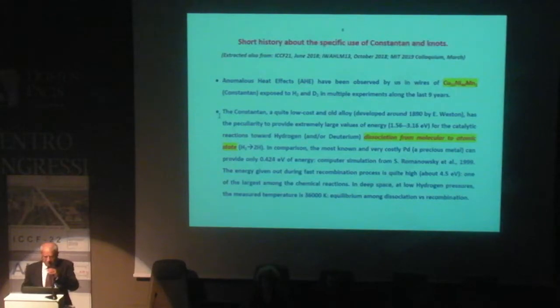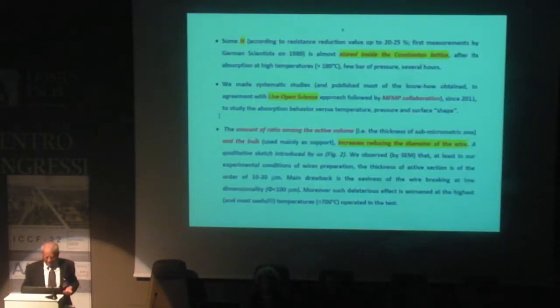Before, we concentrated on using knots, because the knots don't need energy to have non-equilibrium, but they have some limits. So now we just forget for the moment knots and go over. We just use the same constantan because it has a peculiarity to catalyse dissociation of hydrogen and deuterium from molecular to atomic state. Very, very easy. It's the best material for this purpose. And moreover, the hydrogen and deuterium is stored inside the constantan itself. So it's like local reactors, every micro-reactor where you can make the reactions.